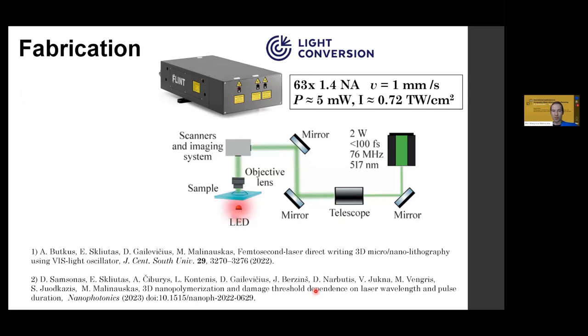Now, a bit more specifics on the fabrication used for microoptics. So femtosecond laser, for our purpose, it was a sufficient femtosecond oscillator, but as Saulius mentioned, the main important parameter is to reach terawatts per square centimeter intensities at the sample using tight focusing. So these are the typical values, looking pretty small, like milliwatts in power, around terawatt in intensity, and we can achieve repeatable scanning speeds of around a millimeter per second for producing microoptics.